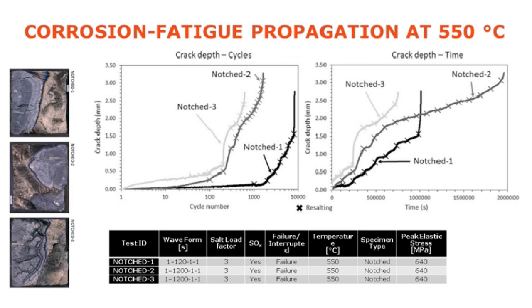If we have a look at how this works out on a time basis rather than a cycle basis, we can see the story's a little less clear. Notch 3 and notch 2 again have some fairly big jumps early on. We've got more stress corrosion cracking going on, but they've not increased at a higher rate because there's less fatigue dominance going on than in the notch 1 specimen. So there's no clear correlation in terms of time to failure in this case, because I think the mechanism is a bit more complicated than the SN curve depicts.